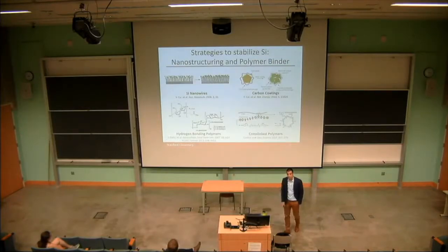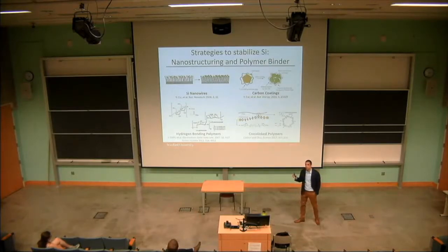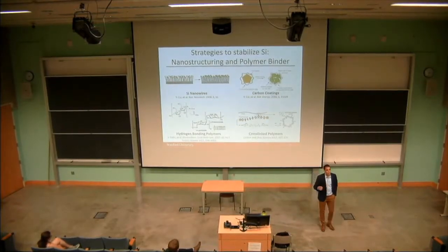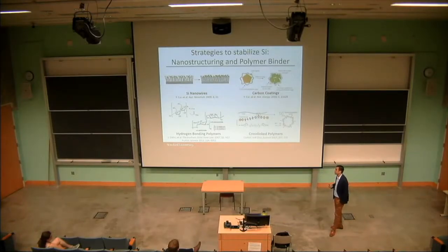To that end, there's been a really large amount of study in this area from a lot of different perspectives. One of the main ones, and I've talked with some people who are working on this here today, is using nanostructures. So when you go below about 150 nanometers in a critical dimension, your silicon actually stops fracturing, and it expands and contracts reversibly. And so when you have this nano size, you can keep the particles from failing.